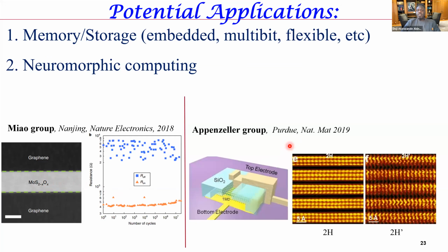Very nice work towards this end was also shown by my very esteemed colleague at Purdue, Jörg Appenzeller, who showed that besides this phenomenon that I described, another phenomenon also exists in certain 2D materials. In this particular case, this is MoTe2 received from NIST, from Sergey's group. And what they claim to be the responsible physics is that in a normal 2H phase of the MoTe2...